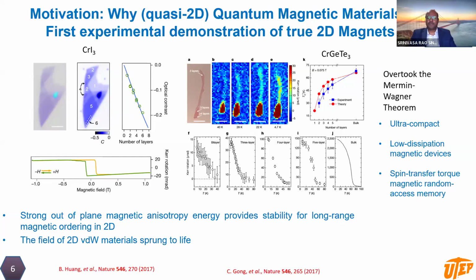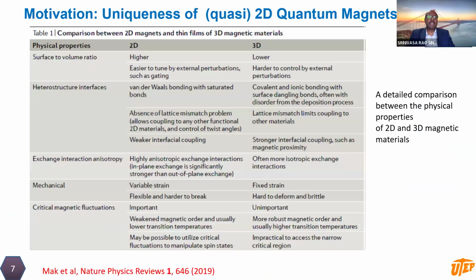That motivated our group to get into the field of quasi 2D magnetism. There are some reasons why we should care about 2D materials versus 3D materials. For instance, 2D materials offer a high surface to volume ratio, and we can seamlessly make heterostructures with different materials because of weaker interfacial coupling and almost negligible dangling bonds. Out of all, the one that caught our attention for magnetic property study is that the exchange interactions in these materials are anisotropic. It means that if you rotate the crystal or a layer, we see strong anisotropic behavior compared to